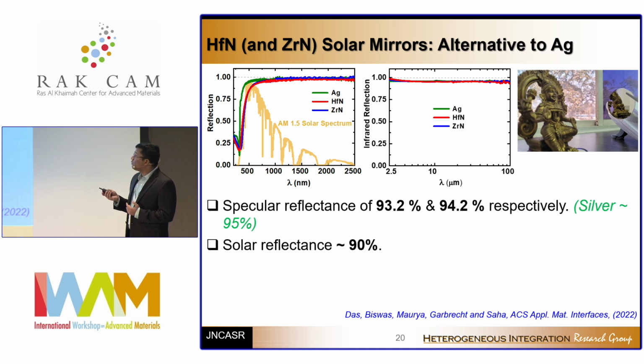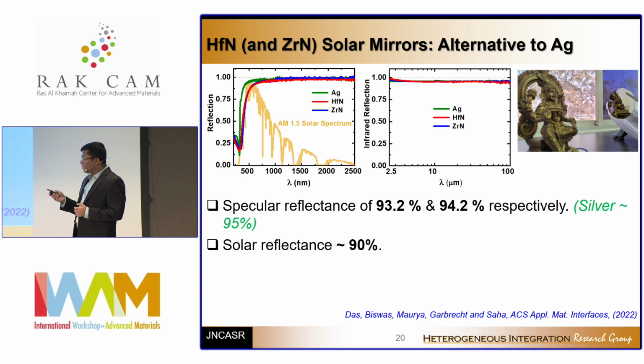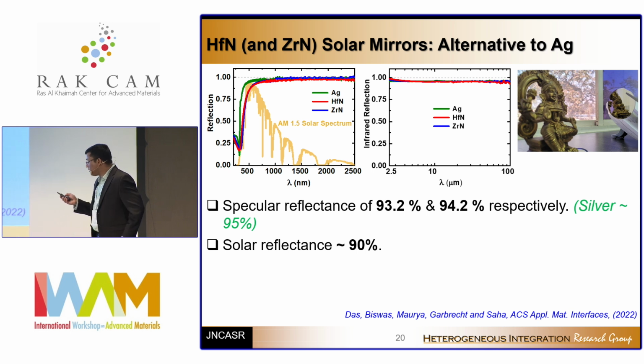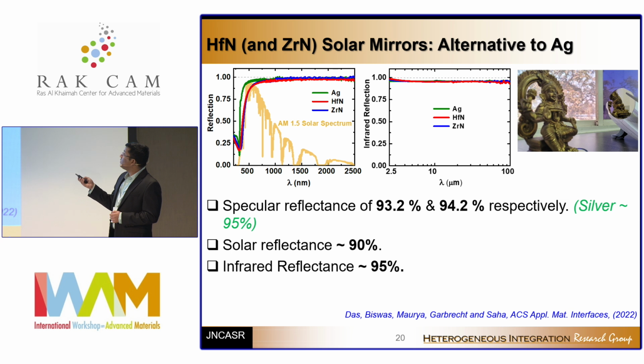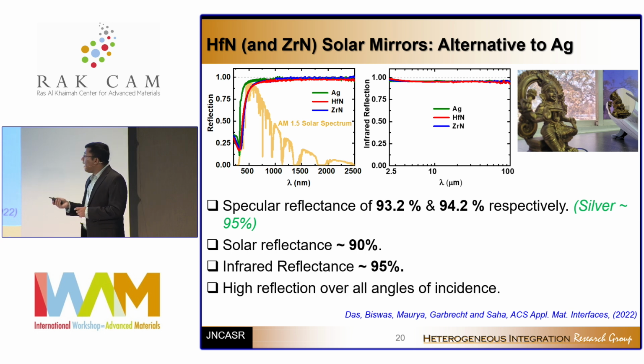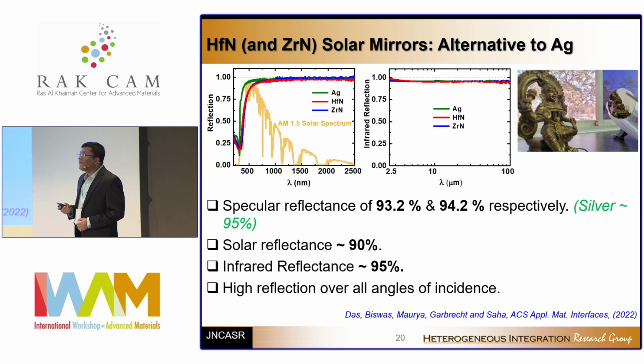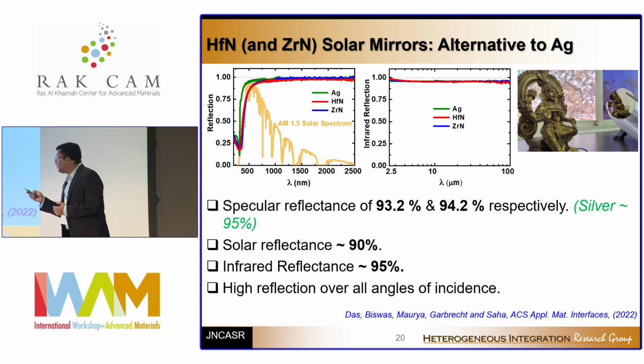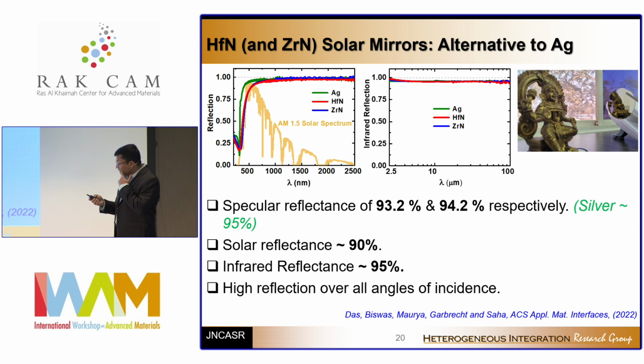We also looked at this, this was the specular reflection at one particular angle of incidence, and solar reflection basically integrated over the solar spectrum also shows very high solar reflectance of 90%. Infrared reflection, as you can see, is about 95%, a perfect flat line, and this is true for all angles of incidence, basically. So in that sense, it's very good.